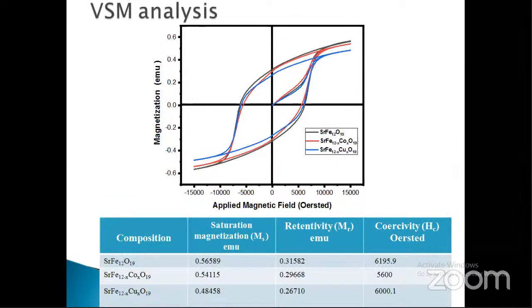And this is the VSM analysis of strontium hexaferrite nanoparticles. This curve clearly shows that the coercivity of the strontium hexaferrite nanoparticles decreases with cobalt and copper doping. The retentivity also decreases, and saturation magnetization also decreases.